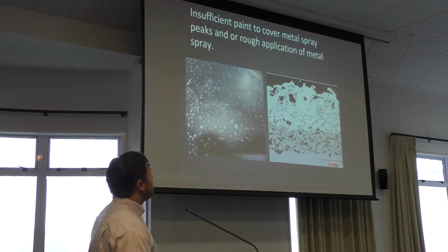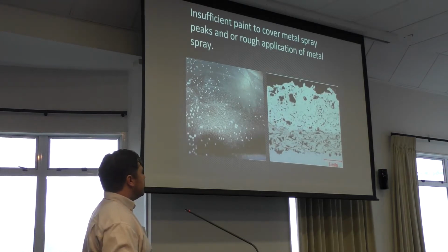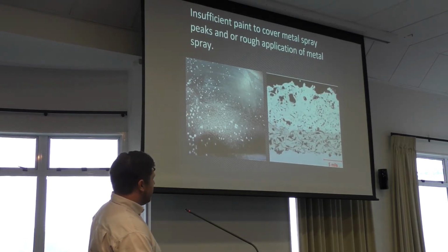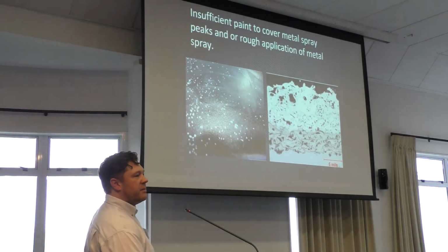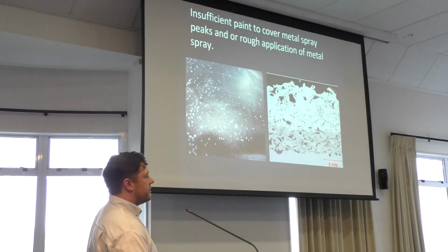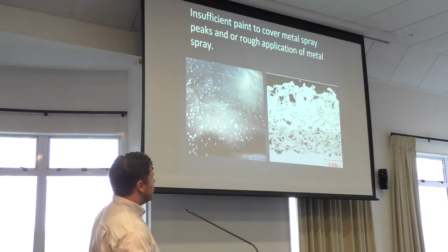Insufficient paint to cover the metal spray peaks. So this is another SEM. You can see that we have the surface profile after we've sprayed. Really, we need to be covering those highest peaks with a minimum to create a barrier. So if they say 40 microns of paint, you want 40 microns over that, not 40 microns over the average of it.